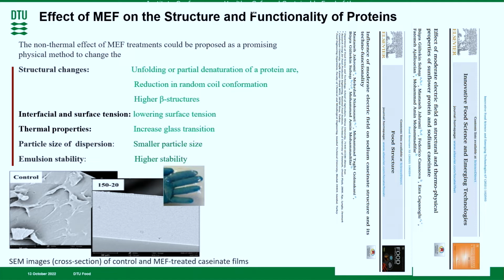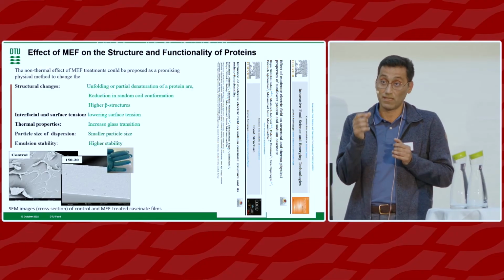We were able to lower surface tension and interfacial tension by the use of electric field treated protein. We changed glass transition. Glass transition moved to higher temperatures, which is important also. And then apparently we have been able to change the aggregation pathways. So we ended up with a small particle size, which is important when you want to make a concentrated protein-based drink. You want to add more dry matter, but you still want to have fluidity. This is a big challenge now.